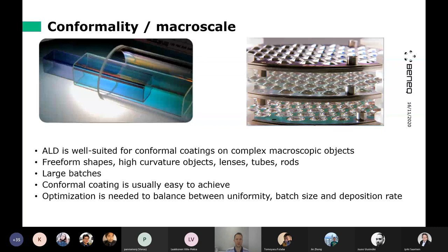But optimization is definitely needed when trying to make uniform enough films on a large batch and fast enough. And this is especially a challenge for optical coatings, where typically the film thickness needs to be easily in the micrometer range, which is thick for ALD. So it means that it will take a long time. So we have to do it as quickly as we can. And also we need to use a large batch size to compensate because anyway we are slow.